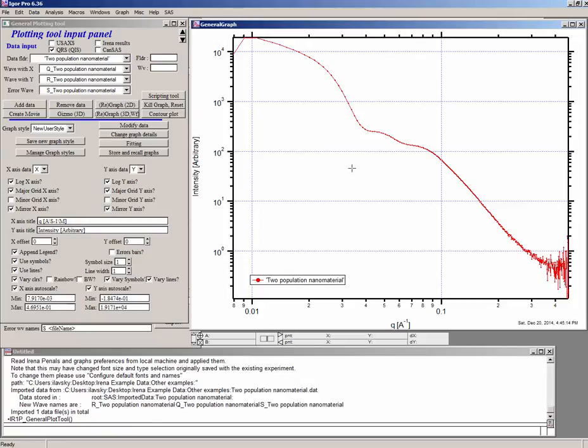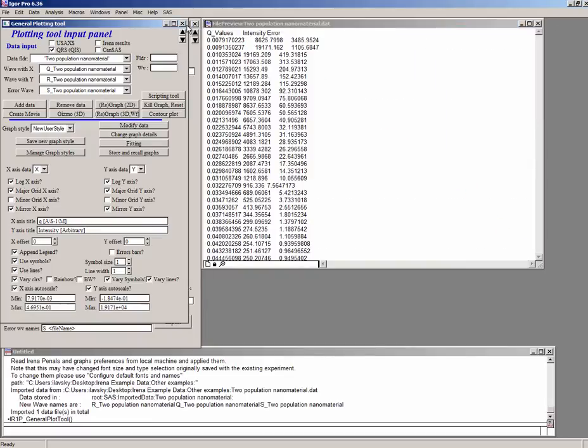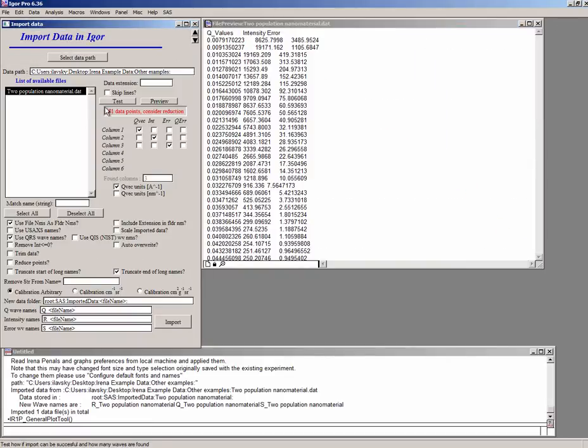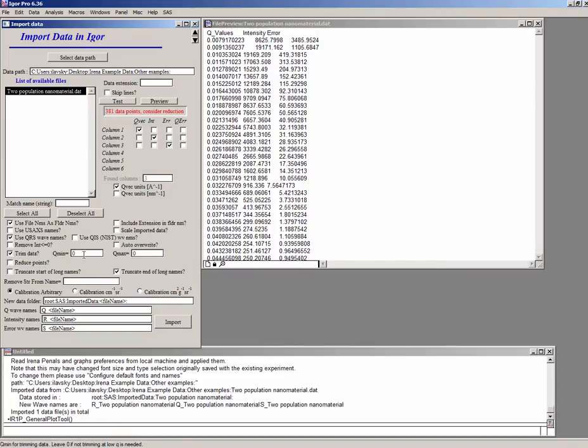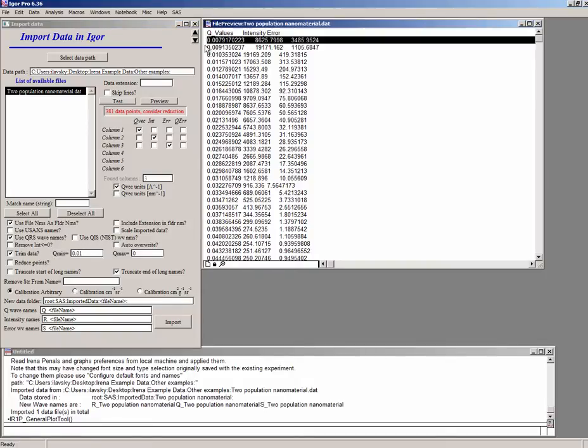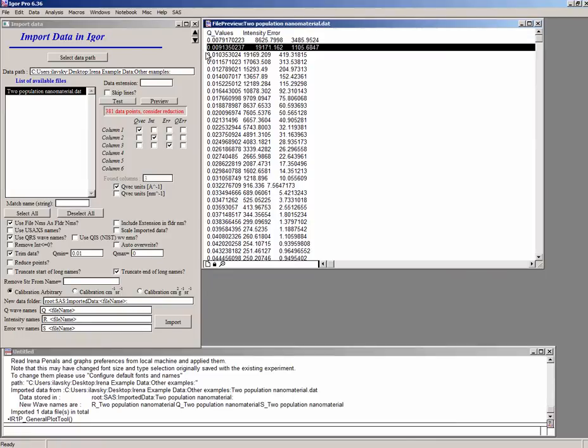So, now we're looking on this data. So obviously we want to trim this start and we want to do some kind of rebinning on that. Let's go back to the import tool and see if we can do it. So I'll close these two windows and we go back to this one. First thing is we can set trim data. If we set trim data, I said anything below 0.01 seemed to have been on the graph wrong. The first point clearly has less intensity than the second point. The second point has about the same as the third point, which it really should not in this case. And then only the real data start.